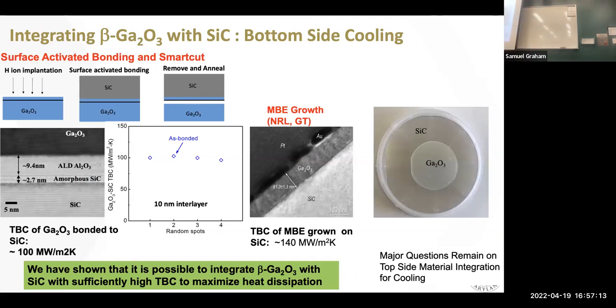Yeah, so again, for a lot of these, you're seeing this thick wafer. I'm mentioning it, but I didn't talk about it. You use what's called smart cut, so you get ion implantation here. So you'll implant it to a depth, maybe 10 nanometers, 20 nanometers. And so we'll remove it, so we'll have a very thin layer. I think the highest that we've gone to is about 40 nanometers.